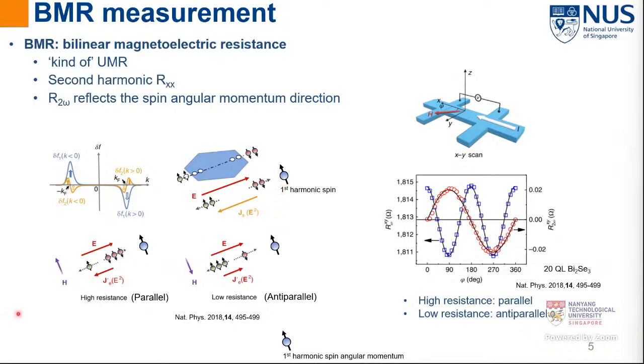However, when there is a large external field, there will be an imbalance between the k and minus k space. In this case, there will be an equivalent charge current. Depending on whether the equivalent charge current is in the same direction as the current flowing, the second harmonic Rxx can show a high resistance case and a low resistance case. So with this conclusion, we can think that when the external field is parallel with the first harmonic spin, it's the high resistance case. If the external field is anti-parallel to the first harmonic spin, it's the low resistance case.